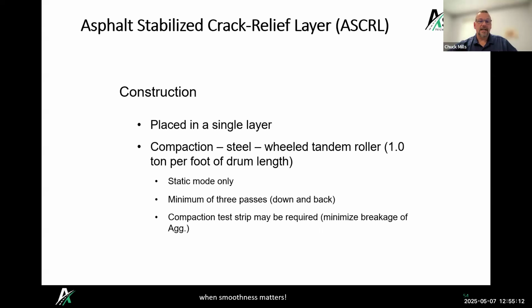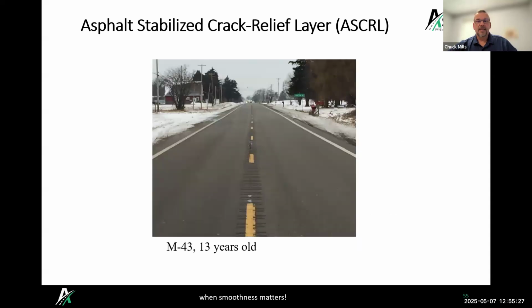It's constructed, placed in a single layer, typically 2.5 to 4 inches thick. We're just compacting it with a steel wheel roller. We're not trying to get density on it. We just basically want to seat it, similar to what we do with the porous asphalt. And it has been working very well. MDOT uses this on a lot of different roads.